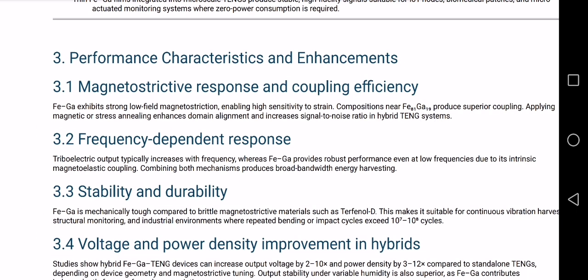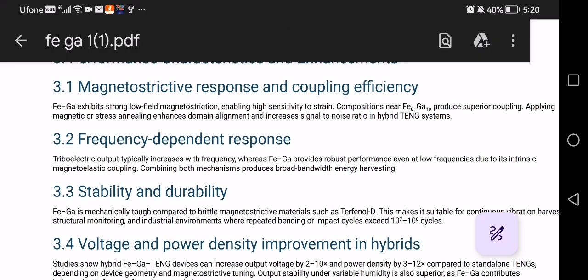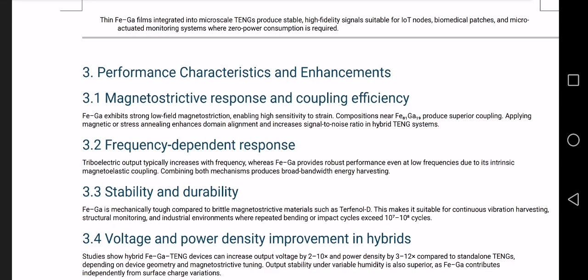Next, we have performance characteristics and enhancements. Magnetostrictive response and efficiency. FeGa shows strong response at low magnetic fields, best composition Fe81Ga19. Performance is enhanced by magnetic annealing and stress annealing. These processes align magnetic domains and increase the signal to noise ratio. Okay.